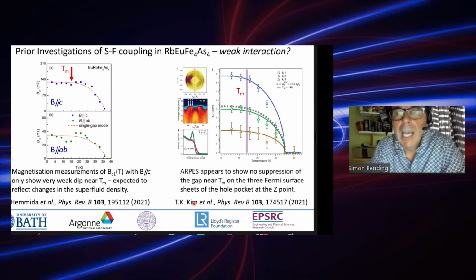Likewise, in these very recent ARPES data from Kim et al., in this paper, they've measured the gaps on the 3 Fermi surface sheets of the hole pockets at the Z point, which lies vertically above the gamma point at the edge of the Brillouin zone. So there are 3 different sheets here. The inner one is the one with the highest gap, and the outer one is the one with the lowest gap. But again, if you look near the magnetic ordering temperature around 15 Kelvin, it's very difficult to resolve any reduction in the gap, any suppression in the gap at all. So that's quite interesting.